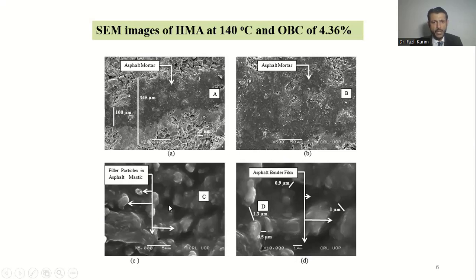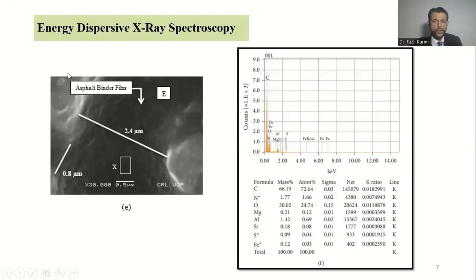Same asphalt mortar. Here, we can see filler particles in asphalt mastic. Asphalt mastic is a two-phase system containing bitumen and mineral filler. Similarly, we can see blurred asphalt binder film thickness, which is clearly visible in the next slide. So now this is clearly visible asphalt binder film among the filler particles, when the image was taken at magnifying power of 30,000 and bar scale of 0.5 micrometer. And now I would like to say that pure asphalt binder film only exists in the asphalt mastic. Wherever we went in the asphalt mixture, we couldn't find pure asphalt binder film. The only place where we found asphalt binder film is asphalt mastic.